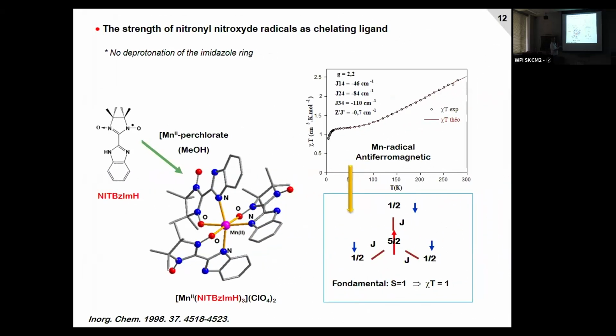So now I will show you the manganese 2. This is manganese 2, 5 electrons, and 3 radicals. When we look at the chi-T product versus temperature, at room temperature, the value is more than 2. Manganese 2, 5 electrons, the chi-T product is 4.8. You also have 1, 2, 3, you have 1.2 for the radicals. So if the radicals and the manganese 2 were not coupled, you would expect a chi-T value of more than 5. Here, the value is lower, which means that you have anti-ferromagnetic interaction.